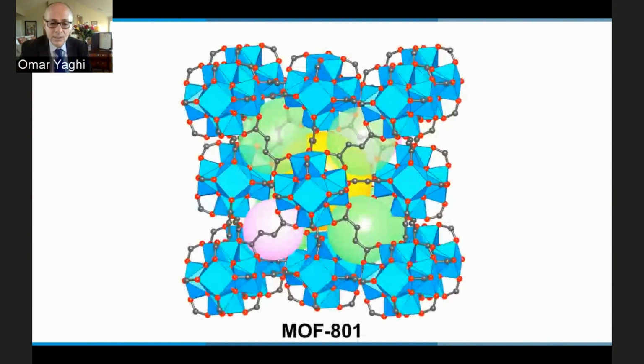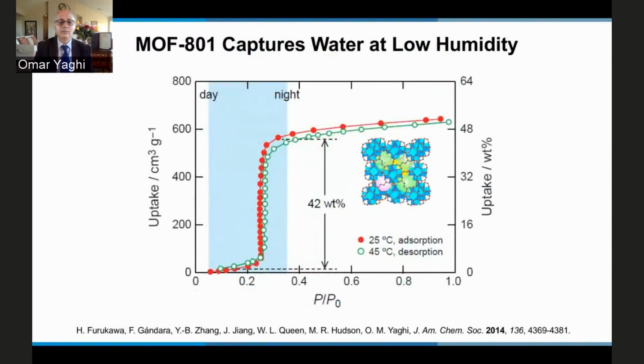So the way we discovered water harvesting from air was during our experiments studying the interplay between CO2 and water, since when you're binding CO2 from air, you also bind water. And we discovered that for this MOF, 801, which is a zirconium MOF, the isotherm for water was very unusual in that it took up water at relatively low humidity, around 20% relative humidity, and took lots of it in a sharp isotherm. And we can take the water out at 45 degrees Celsius, so at relatively low temperature.